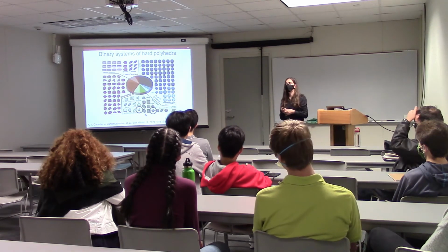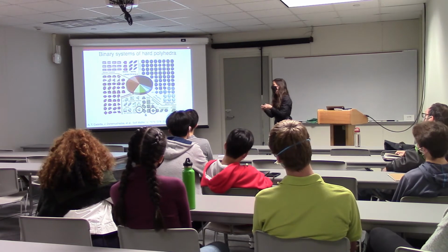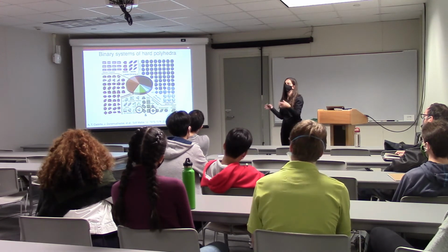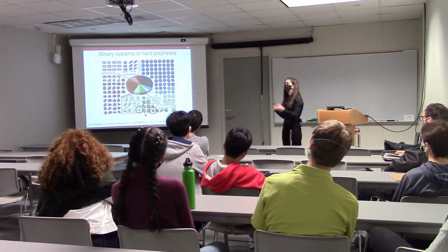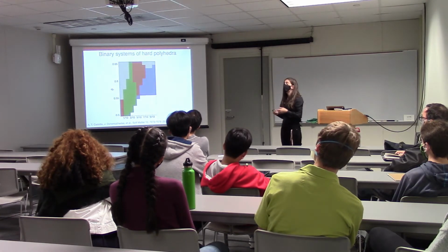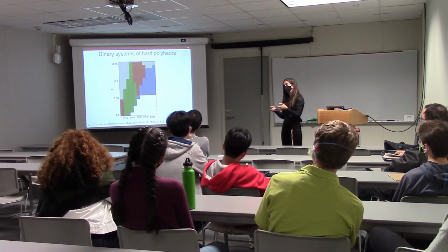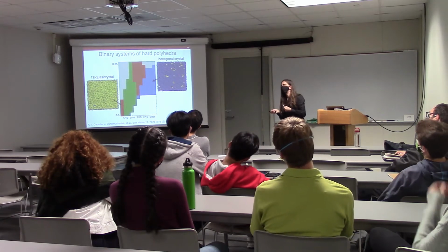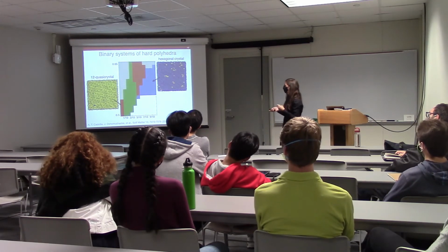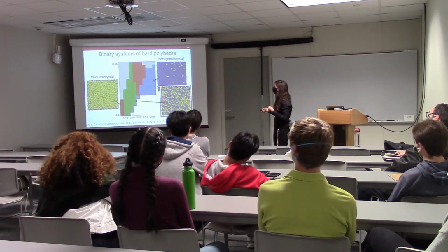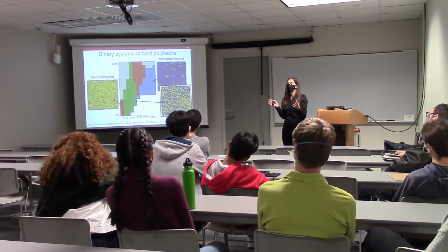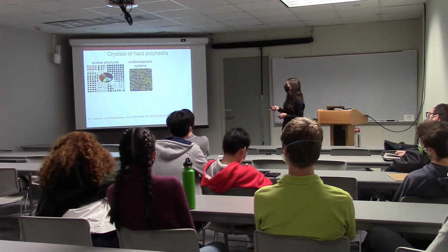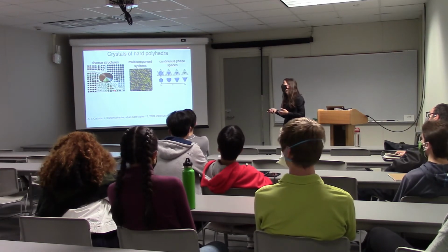Other fun phenomena are, for example, that if you mix those shapes together, and you do it wisely, so you have a really big shape and a really small shape, what's going to happen is phase separation, and it's not very exciting. If you mix them together and they're as similar in volume as tetrahedra and octahedra, you can observe the formation of compounds. So you have your quasicrystal over here, your boring octahedral crystal, I think there's hexagonal symmetry, I actually am not sure anymore, over there, and in between you have a nice compound crystal structure with a completely different symmetry. So they want to form a structure together that is otherwise not observed. So you see multi-component systems that form their own crystal structures.